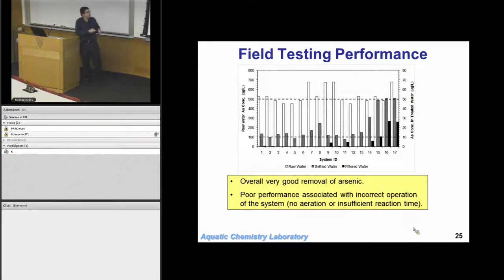And this technology really can work. So we drop it down to 100 just in the settled water, and if we then filter it, in most cases we can get down well below even the 10 micrograms per liter standard. A few cases it didn't work well, and they went back and realized what was happening is that people either weren't aerating the system or they weren't giving it sufficient reaction time. But I would say in probably 14 out of 17 cases it was a good technology.